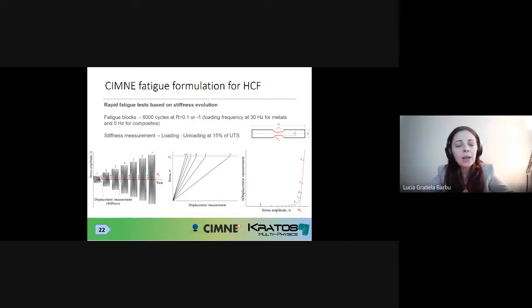Specifically, for high cycle fatigue that has lives of millions of cycles, you need about 2 weeks to a month of having a testing machine doing these tests. It's completely blocked for that material and that specific geometry. So in the Fatigue for Light project that we have in our group, we've worked together with Eurecat and with ArcelorMittal to design a testing strategy which significantly lowers the experimental time needed for fatigue experimental characterization.